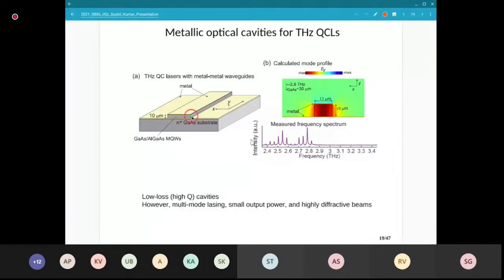So making this is another aspect. These layers are grown on a semiconductor substrate, so we need to somehow get rid of the substrate. The way it's done is you deposit metal on top of the structure and flip chip bond it. So there is wafer bonding involved and substrate removal, and it's a fairly challenging process. That has been developed over time, not in our group, when I was a PhD student and in some other groups, and it's been perfected, but it still takes a lot of effort. Every time a new student is on the project, it takes them a year or so, or sometimes more, to get this going.